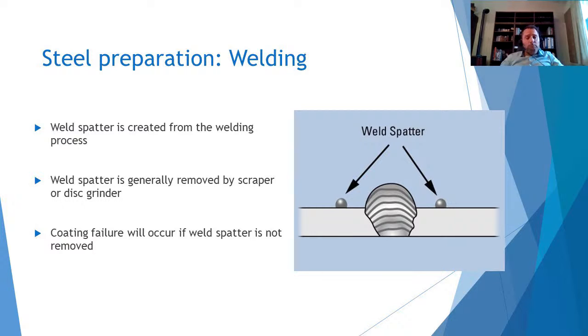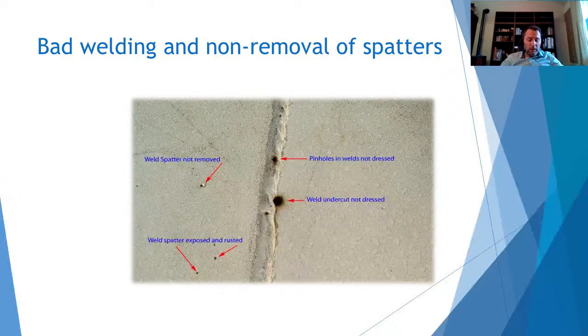We have a picture of bad welding and no removal of spatters. Weld spatters are particles of molten metal from welding on the surface adjacent to the weld. Weld spatter can be removed easily with an impact tool such as a chipping hammer, but general removal requires grinding with a disc or angle grinder. Another defect is pinholes, evident in these pictures.